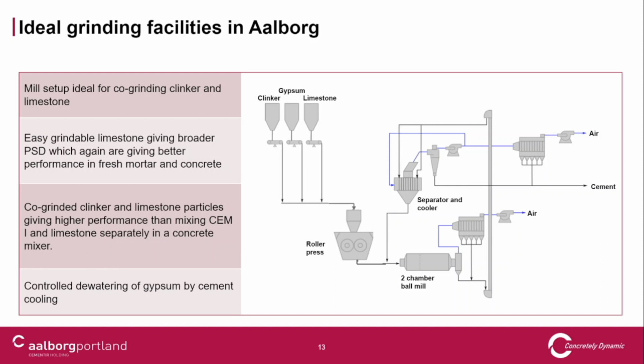Here at the plant we have a quite advanced milling facility for white cement production. We were talking about particle size—Luke was asking whether it could be better to grind these materials separately instead of co-grinding and blending. This is only limestone, not clay, but with our milling facility, shown here in a sketch, we actually have very good possibilities to co-grind the limestone and clinker.